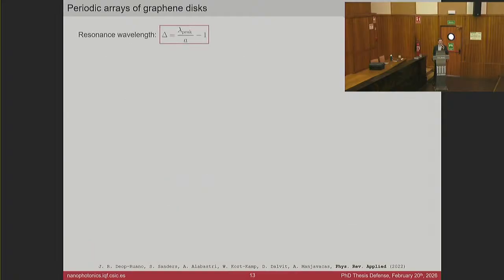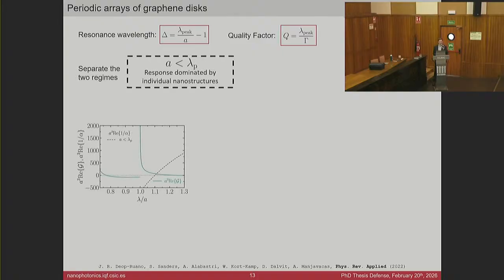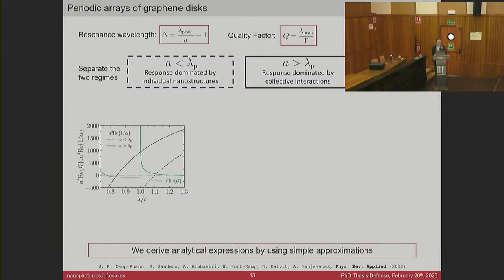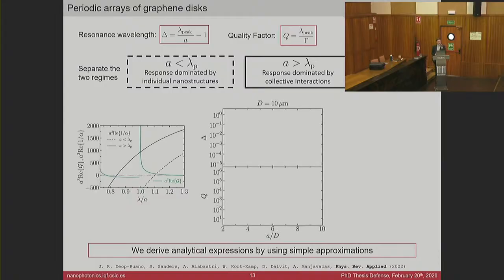Now, we can also derive analytical expressions for the rest of the quantities characterizing our resonance. It's going to be a bit faster here: the resonance wavelength and the quality factor. To do so, we can separate into two regimes. First, the regime in which we don't support lattice resonances, so the response is dominated by the individual nanostructures. In this case, the inverse of the polarizability crosses the lattice sum in a region where the lattice sum is not large enough, and the opposite regime in which we have really large values of the lattice sum. This allows us to derive some closed form analytical expressions,